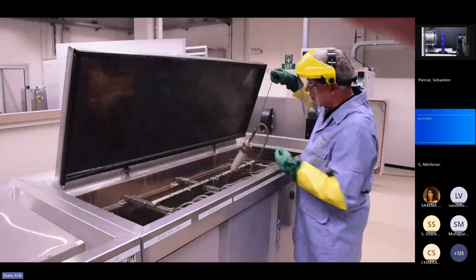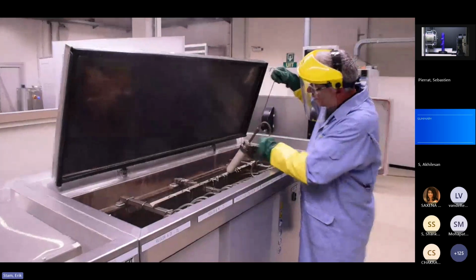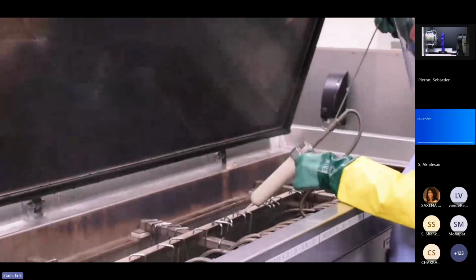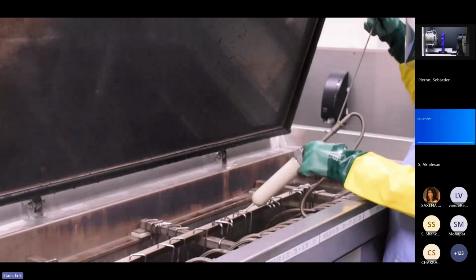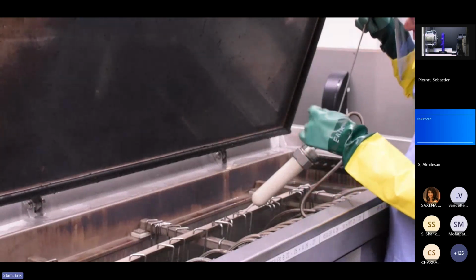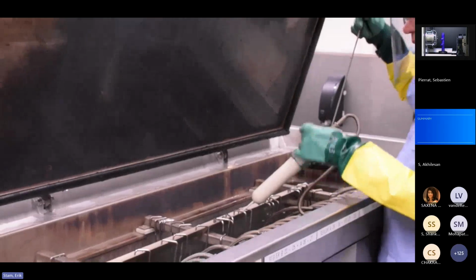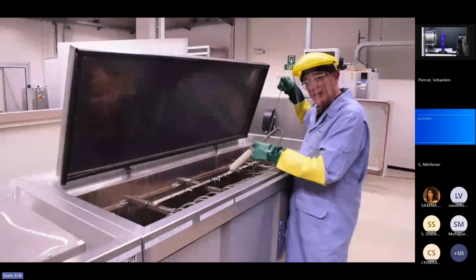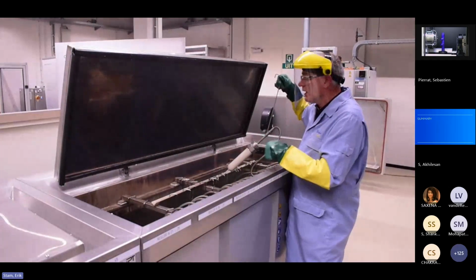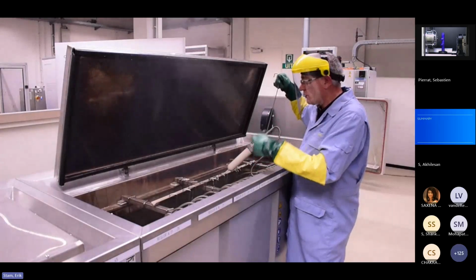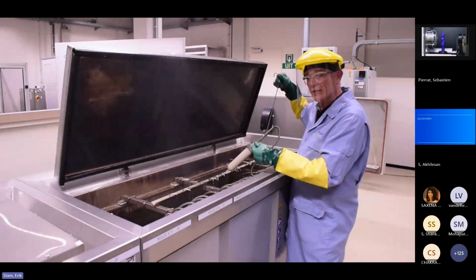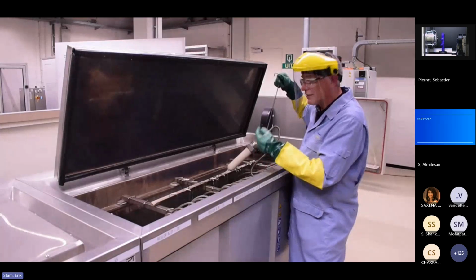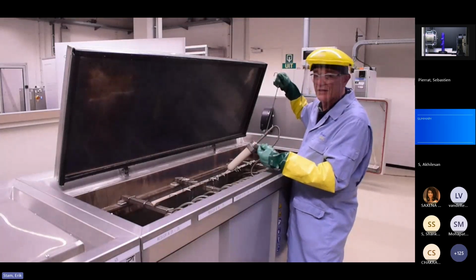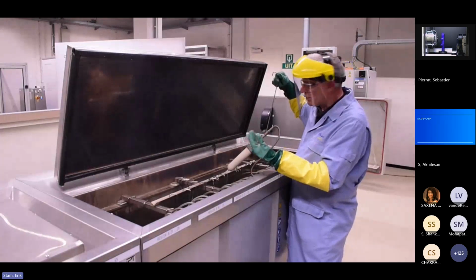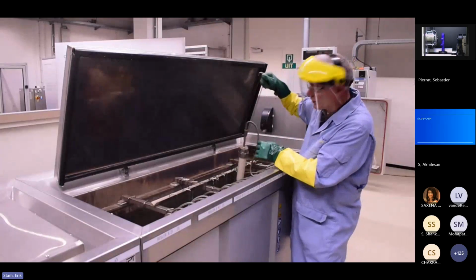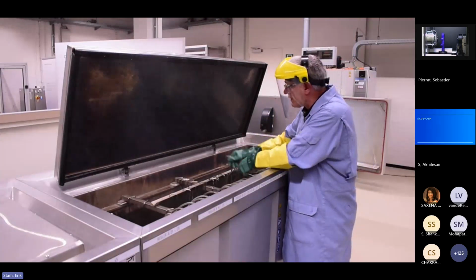The water bath is used as a medium for the temperature. So you can see a sample here. What happens is that you put a constant pressure on it, and at one moment it fails, and the failure mechanism is called creep rupture. The failure mode also changes from ductile failure mode in the beginning, and if you continue for a longer time at lower stress levels, it will come to a slow crack growth. And in the end, if the material starts to degrade, then you speak about degradation mode. The last phase you never want to be in, because that means that your material would not be suitable for water applications.